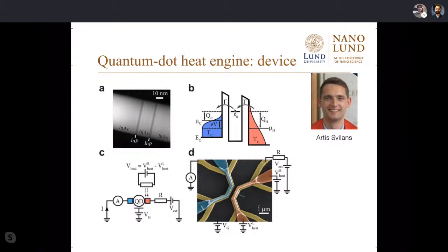You have individual energy levels that are quantized by Coulomb interaction primarily. You have the ability, with our heater systems, to heat one side while to a good degree keeping the other side cold. The quantum dot also acts as a thermal insulator between the two electron baths, so you can maintain that temperature gradient. Then we hook everything up to a circuit so that we are able to measure the current driven by that delta T across the quantum dot.